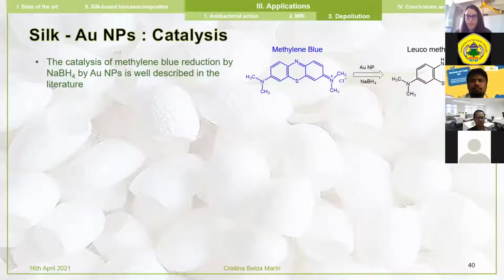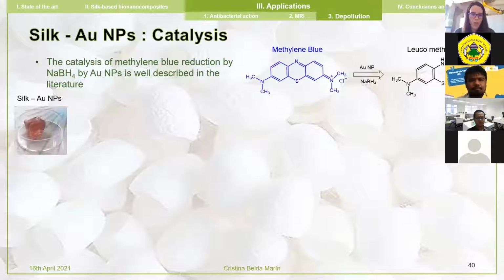So methylene blue, I didn't say, is a model molecule that we have chosen, but it's very used in the industry and it's toxic, and it's pretty much released into the ocean. So it's a major problem. So it has been shown in the literature that gold nanoparticles can catalyze the reduction by sodium borohydride, and it catalyzes its reduction to leucomethylene blue, which is not toxic and not colored. So it's very good for our experiments.